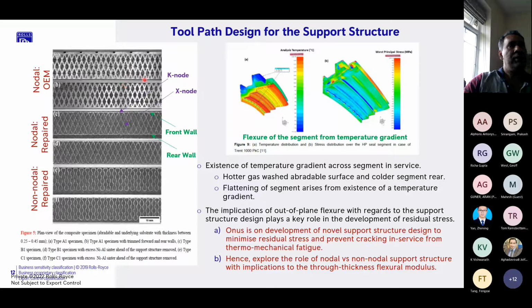Now, the thing to keep in mind here is that when you put this segment into service, you've got an abradable there, you've got an abradable here. This segment actually operates in a temperature gradient. The portion of the segment which has got the abradables is hot because it's in contact with the hot gases, whereas the back of the segment, which is where we've got the hook, is cold. So you've got a thermal gradient across the segment. Therefore, in service, what really happens is this segment begins to flatten. So you get some kind of flattening and unflattening over the course of the service life of the segment.